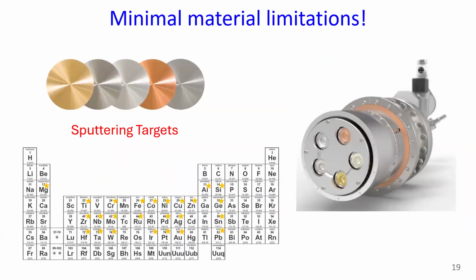But the other advantage is that with this strategy, we're limited only by whether we can get a 2-inch disc of metal in order to have a sputtering target. And so there are very minimal material limitations. Essentially, if a metal can be sputtered, then we can use this strategy to explore that species as part of the design space.